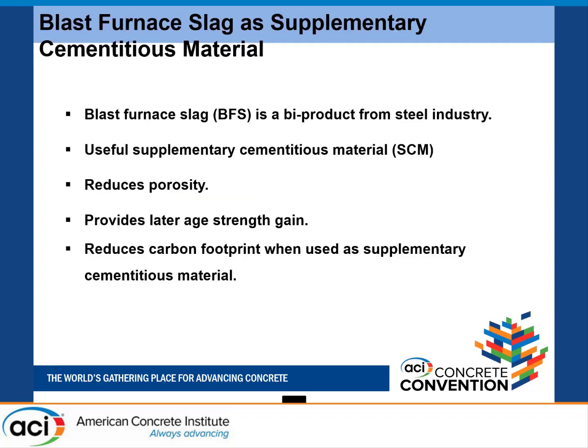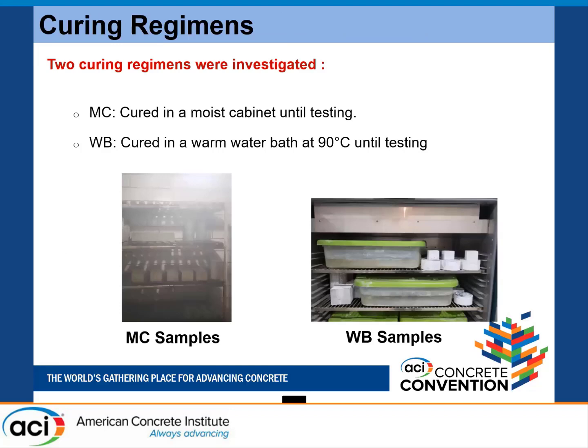Now, in this particular research, we have used two different curing regimens to investigate the effect of heat treatment, how the slag stabilizes the cementitious system under elevated temperatures. The regular one is just a moist curing room at room temperature and almost 85 degrees relative humidity. And water bath curing basically simulates the steam curing in precast plants. So basically what we did is that we took a plastic tub with water and placed it in an oven, set that oven at 90 degrees Celsius, and all the specimens were cured under wet curing conditions, but at 90 degrees Celsius to simulate the steam curing. These are the two curing regimens that we investigated.